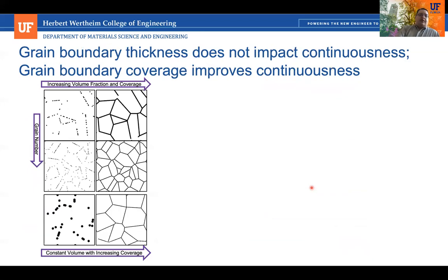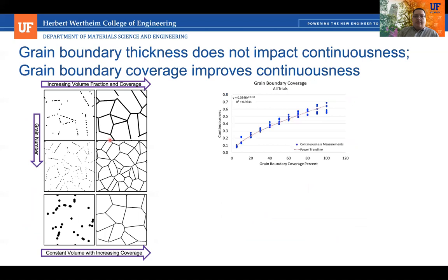The next thing we looked at is how we can improve the microstructures of these continuous structures, where we have the additive around the grain boundaries. And so again, we generated different microstructures and looked at their continuousness. And first off, as we increase the coverage of grain boundaries by our additive, the additive grain boundary coverage, we get a very strong correlation. The more coverage we have, the higher the continuousness, irrespective of other aspects like the volume fraction and so on.